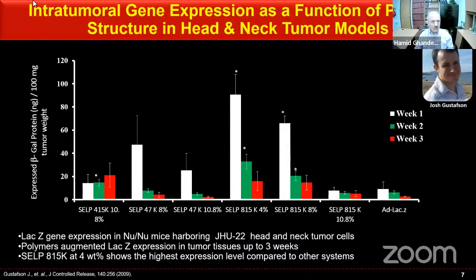And in this case, what is shown here, basically we incorporated adenoviruses in these liquid polymers, and then we injected into the head and neck tumors of basically xenografts of mice. And the key point here is, as a function of the structure of the polymer, as well as function of concentration of the polymer, we were able to control the release of these adenoviruses and gene expression.